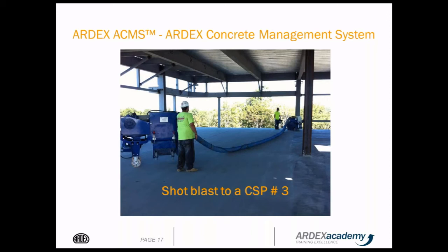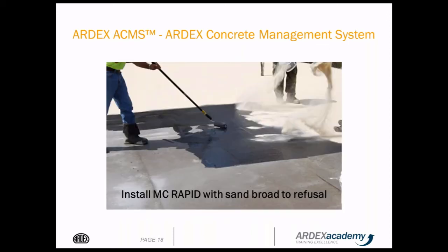It's wide open, so you're just making real long passes. And the fact that the concrete is only 3, 4, 5 days old, you're running at almost 100% capacity of the shot blaster. Roughly 85 to 90% capacity was done on this project, when typically with a shot blaster you're only running at about 30 to 40% capacity, or 30 to 40% total speed, because you're trying to remove contamination. So the speed of blasting in this application is very quick.